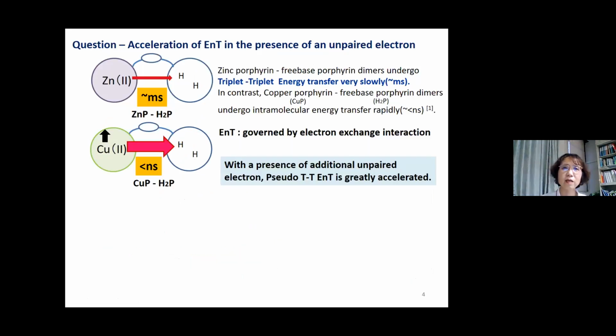So my question is, in the presence of an unpaired electron, how does acceleration of energy transfer occur? This is just a comparison between the diamagnetic and paramagnetic systems. Porphyrin is a very well-known compound which coordinates many metal ions. Zinc porphyrin and free base porphyrin dimers undergo triplet-triplet energy transfer very slowly, usually on the millisecond order. Of course, it depends on the distance between the donor and acceptor.